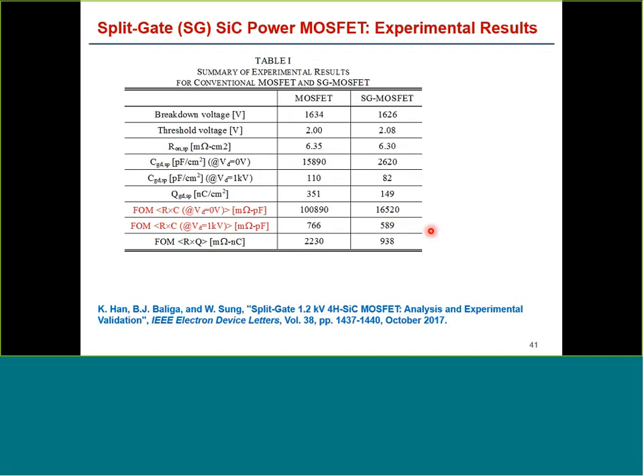So here's a summary comparing the performance of the SG MOSFET and the conventional MOSFET as measured in the devices that were fabricated at XFAB. You can see the breakdown voltages are about the same, threshold voltage, RDS on is also very close, but we have a big reduction in CGD at 0 volts and also a reduction in CGD at 1 kV. Significant reduction in QGD as well.